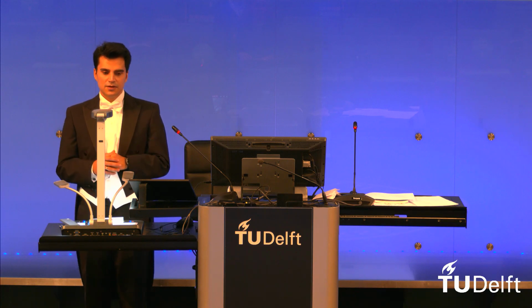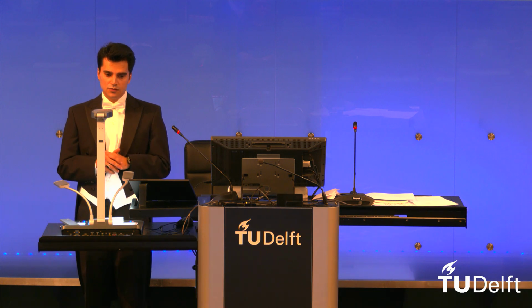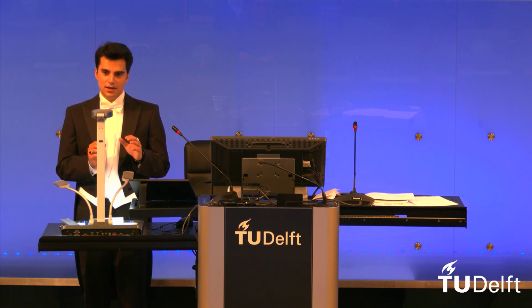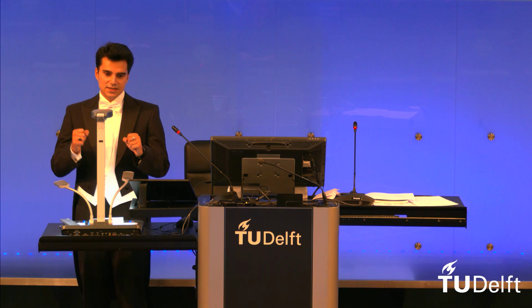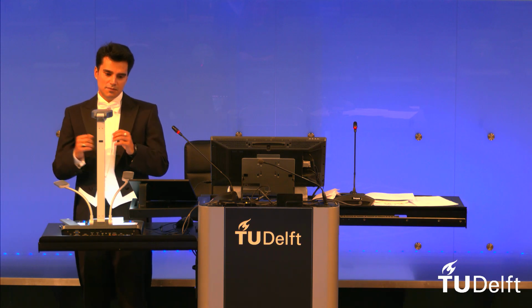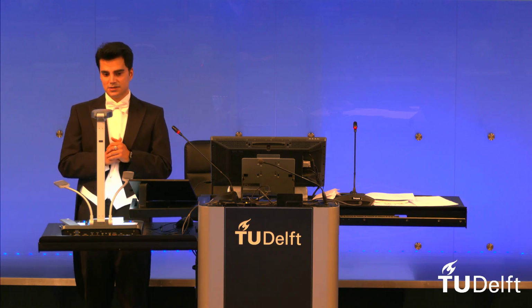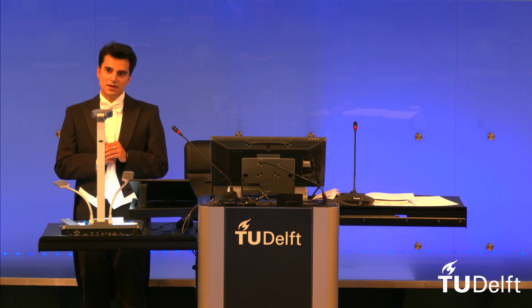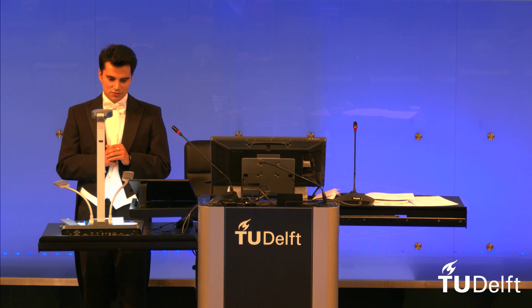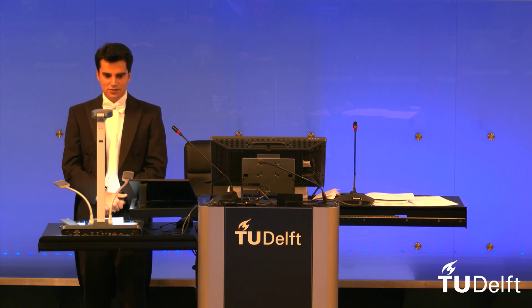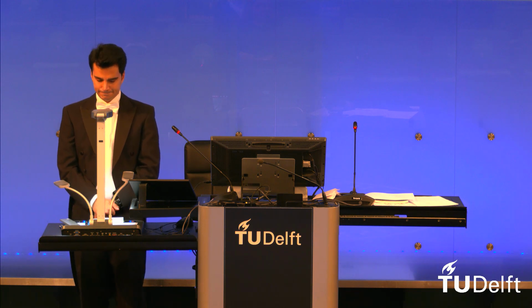On the other hand, when you are watching Taekwondo or Kung Fu, I personally did Kung Fu for a couple of years in my youth period. The idea is to have less amount of contact, but at the same time, very powerful hits. Even if you have a very long period of contact, then the referee is allowed to stop you by fault. So it's kind of comparable with impact loading of the system.